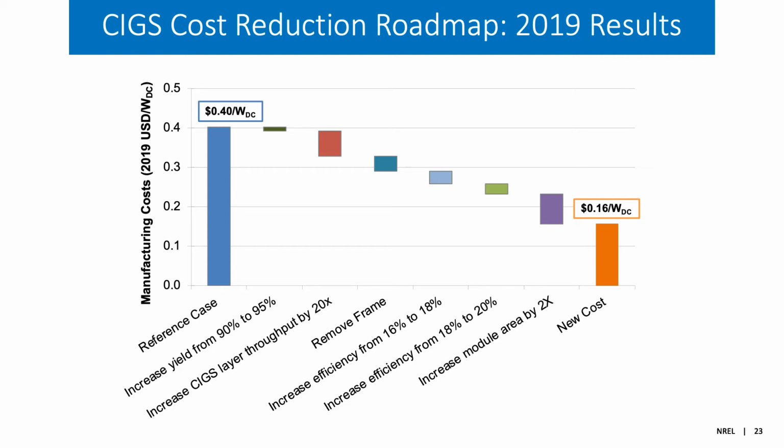So it's really about speeding up that process or finding an alternative. And there are alternatives such as co-evaporation or inline rapid thermal processing for selenization and sulfurization that people have looked at, and we have seen that those can help to improve the throughput of these processes, but are not at the scale of the two-step batch process yet in production.